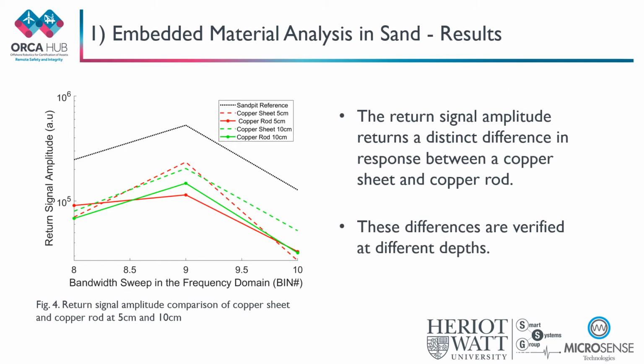Lastly, the return signal amplitudes were then compared against each other for the copper sheet versus copper rod. The results indicate a distinct difference in return signal amplitude at different depths, depending on the shape of material. This enables for detection of shape of an embedded material and therefore potential characterization by development of a library for the copper material and shape. These differences are verified at different depths. This experiment was also repeated for different materials including aluminium, brass, and iron.